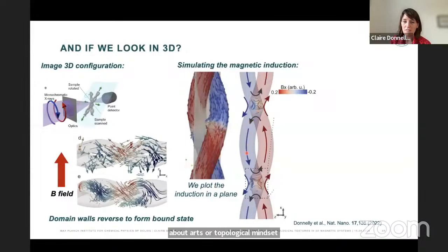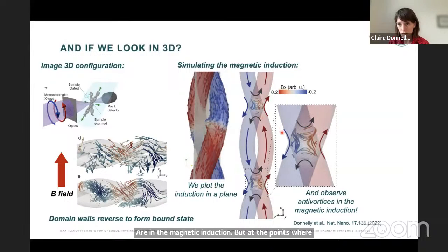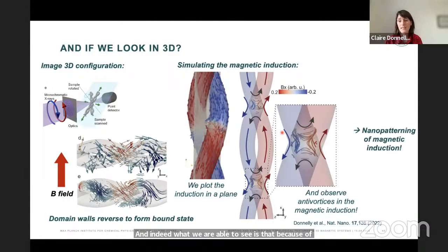Within the magnetization, the chiral structure is forming these so-called effective vortices in the magnetization or in the magnetic induction. But at the points where we have the domain walls, we see something that looks more like this saddle-like structure. And indeed, because of these chiral double helix structures, we are able to stabilize these anti-vortices in the magnetic induction on the nanoscale. So very nice from an interesting point of view. You can draw analogies between cross-tie walls in thin permalloy strips and the magnetic induction pattern that we see in the surroundings of this three-dimensional geometry.